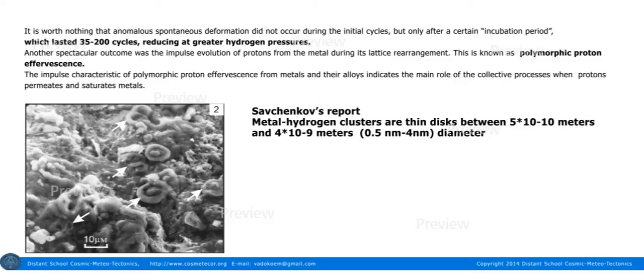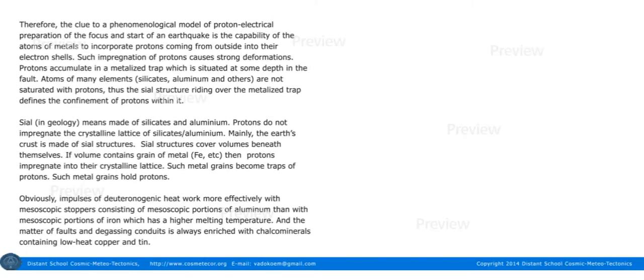The impulse characteristic of polymorphic proton effervescence from metals and their alloys indicates the main role of the collective processes when protons permeate and saturate metals. Savchenkov later reported that movable atomic metal-hydrogen clusters were being observed at room temperature. Those atomic metal-hydrogen clusters are thin disks between 5 times 10 to the power of minus 10 meters and 4 times 10 to the power of minus 9 meters in diameter, and were observed at the side of tension cracking. The surface of the cracking resembles the boiling of liquid.